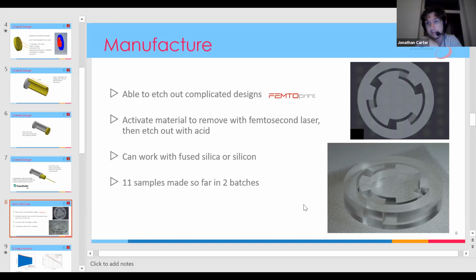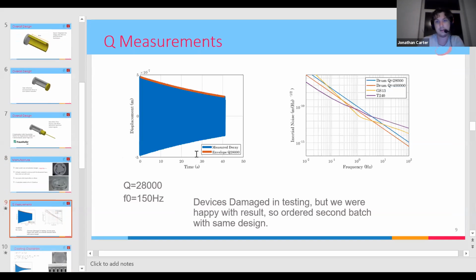They then etch out this material with hydrofluoric acid, and it leaves the geometry that you desire at the end. Their technique works with either fused silica or silicon, and so far we've had 11 samples made in 2 batches. When we had the samples, the first thing we did was measure the quality factor. We did this with just a ring down technique.